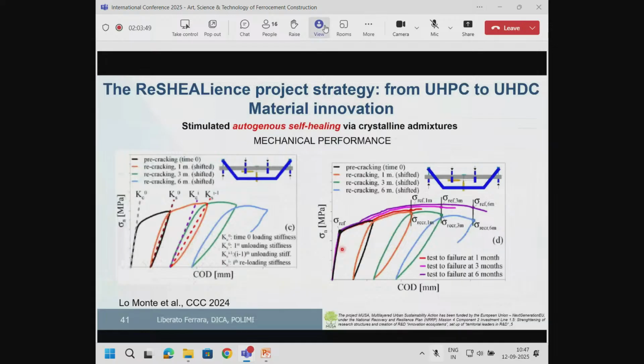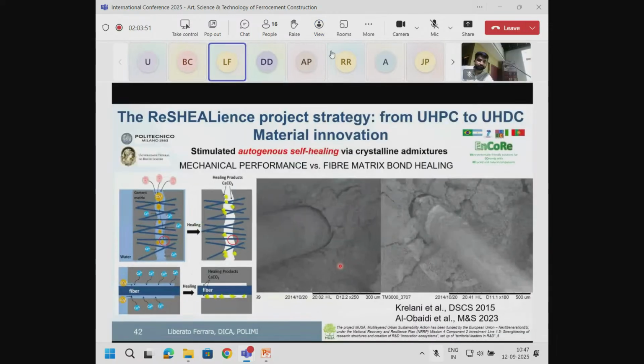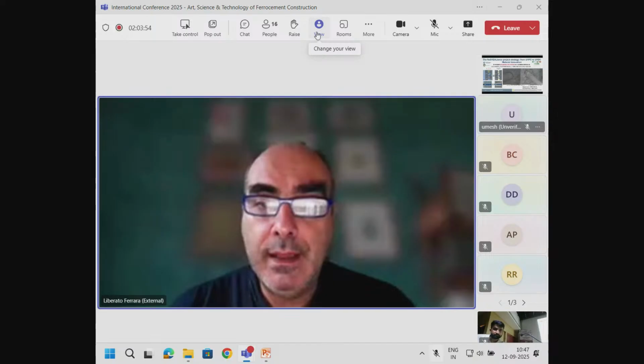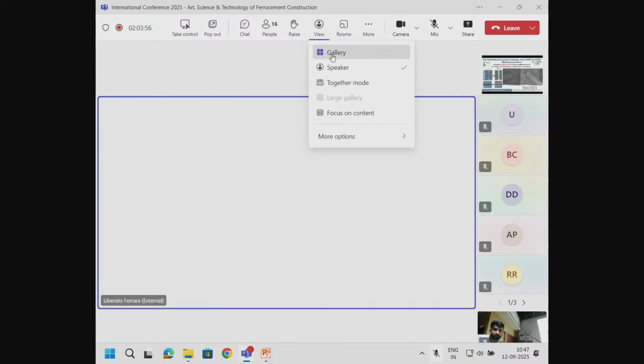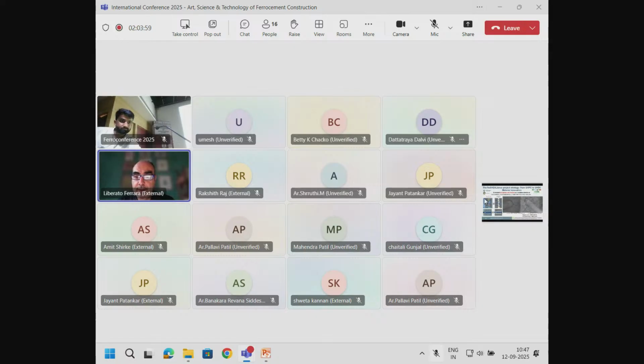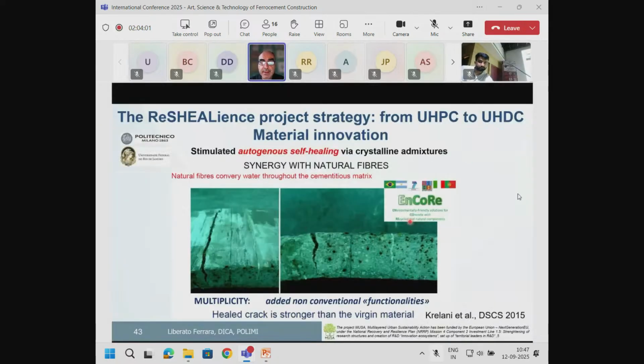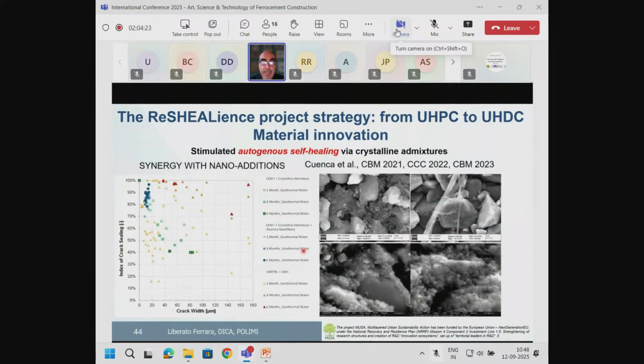capacity of the material to keep the mechanical performance also because of micromechanical interactions between the fibers and the matrix. You can see here all these healing products deposited. And also what we observed, you see, this was a very thin section, very typical of this application, ferrocement or UHPC. And we have a healed crack here. And when we reloaded our material, this crack stayed closed, meaning that it was really strong. And this crack reopened a new formation of fresh cracks.